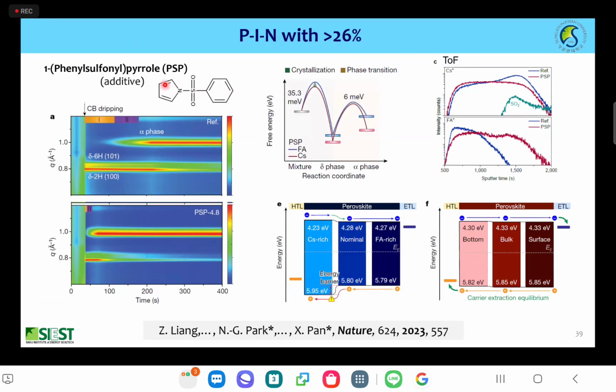And then we introduced this additive, phenyl sulfonyl pyrrole, for short PSP, in the precursor solution. And then using in-situ GIWAXS, the spectroscopic analysis, we found that the activation energy difference can be greatly decreased between FA and cesium. Therefore, we can get a very homogeneous distribution of FA cation and cesium cation across the film. The cesium-rich region can act as a barrier for hole transport. Therefore, after solving this inhomogeneity, we found that hole transport is facilitated.